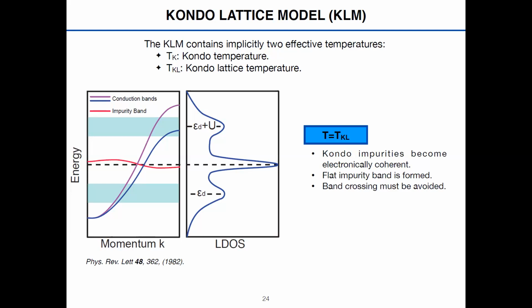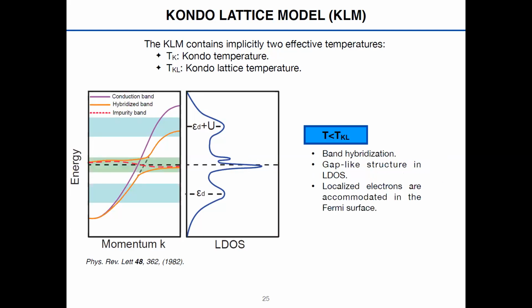However, this flat impurity band is now crossing with some of the conduction bands, meaning that in theory this should be forbidden, and therefore this conduction band is going to hybridize with this impurity band. The hybridization means that your localized moments are no longer localized, they become delocalized, and the conduction electrons that were screening it are acquiring a lot of mass, and therefore here you have your heavy fermion quasi-particles. These heavy fermion quasi-particles are then accommodated in your Fermi surface, and this is why you supposedly have an increase of the Fermi surface of your system.